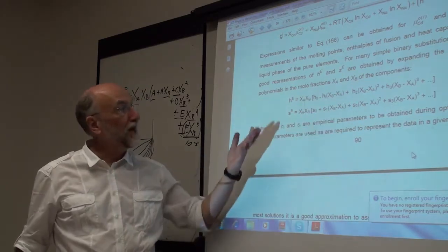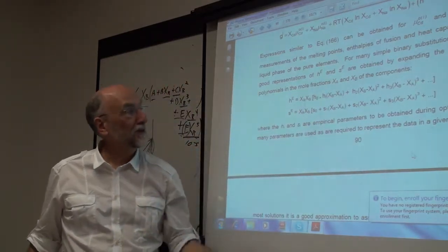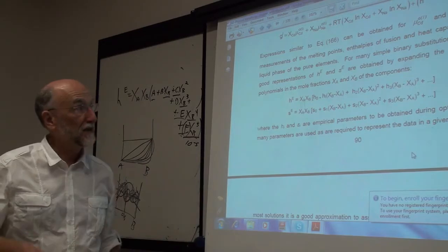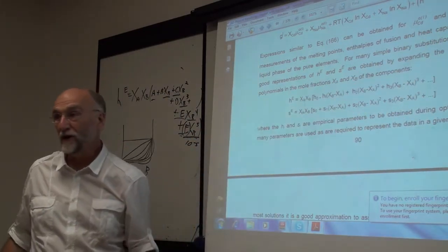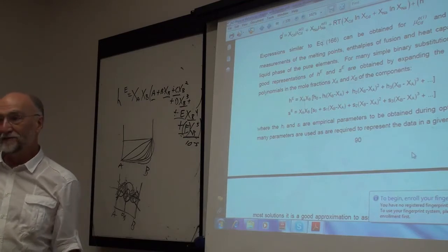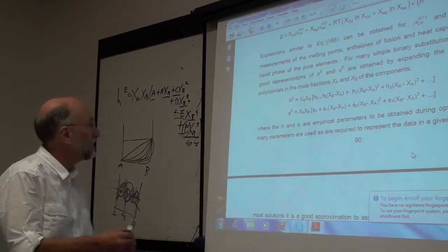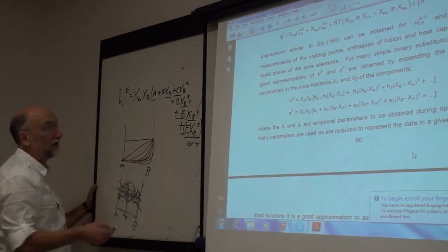Okay, because most thermodynamic properties don't have an x to the 5th sort of character, so they tend to get smaller and smaller. Then you can see that if you add another coefficient and that coefficient is really small, you've probably gone far enough. So you don't have to keep 16-figure accuracy, because again the functions don't get huge on one side and 0 on another, so you don't need extremely large values.